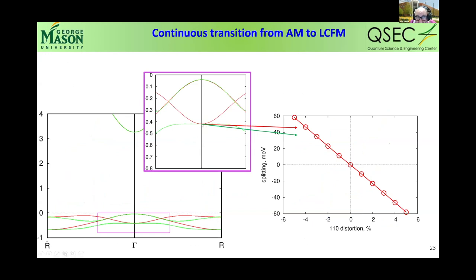Here I plot, for instance, this, you see gamma point. In gamma point, the bands are degenerate by symmetry in altermagnet, but not in compensated ferrimagnet. And this is this splitting plotted as a function of 110 distortion. You see it's perfectly linear, and it's actually not that small. So that means that these things are really genetically connected. In fact, if it hadn't been a metal, there would be also net magnetic moment, also linear in this distortion. So I think I will end at this point and we'll take questions.